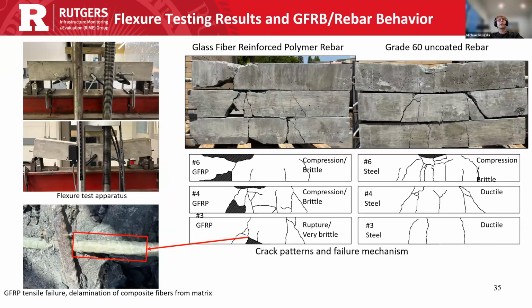So just to get into some of the flexure behavior, you can see the flexure test on the top left, as well as the resulting behavior from these sections. They were tested with GFRP and steel with different rebar configurations, going from number 3, 4, and 6 to represent under-reinforced and over-reinforced sections. So we can see that with the GFRP, all of the beams failed in a brittle manner, as is characteristic of GFRP-reinforced sections. So the over-reinforced sections broke in compression, so a brittle failure, concrete crushing, and the under-reinforced section ruptured, and that's a very brittle failure that the code tries to eliminate because it is a more sudden failure mechanism.